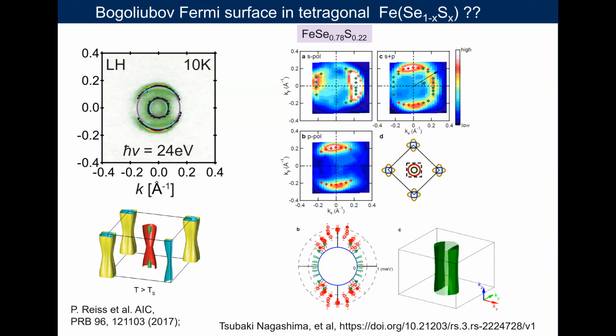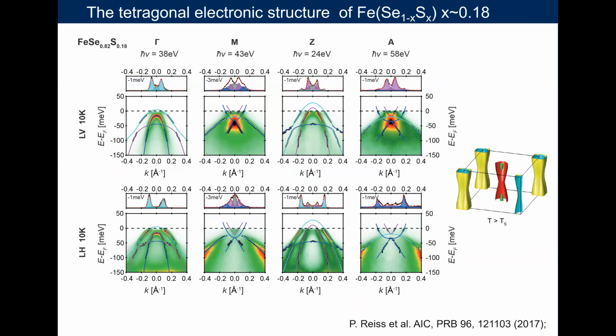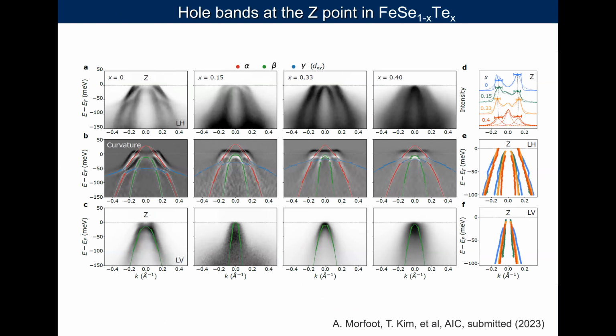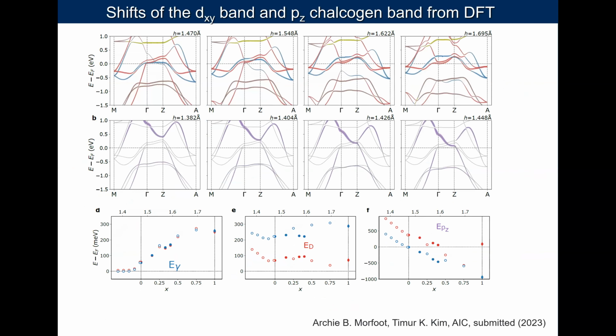From, assume that there is a spin fluctuation driven mechanism for this. You mean from a neutron diffraction? So I mean, you have this gray gradient plot where you looked at the. So that's the NMR data show that there are spin fluctuations, but they do not tell us how anisotropic they are. I'm not aware. To test the anisotropy in this material, you need to detwin your samples. Otherwise, you measure an average effect.